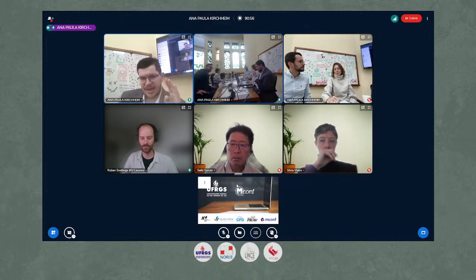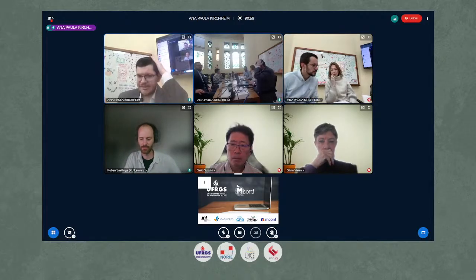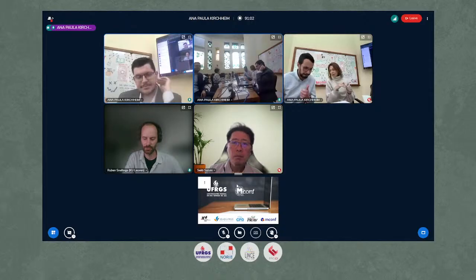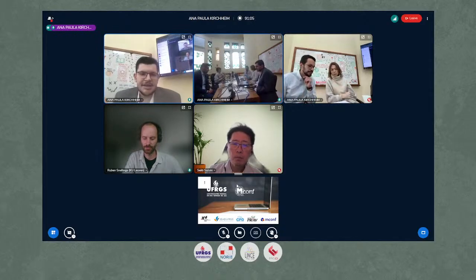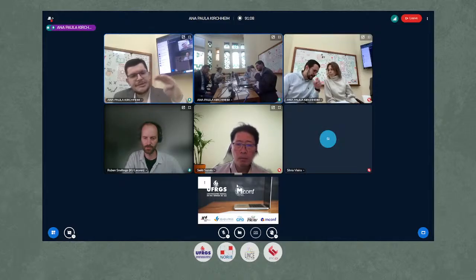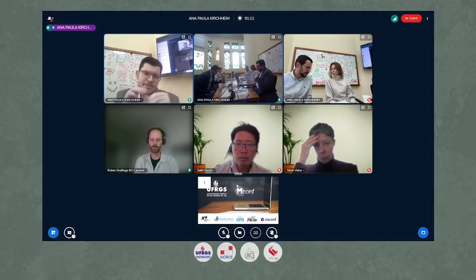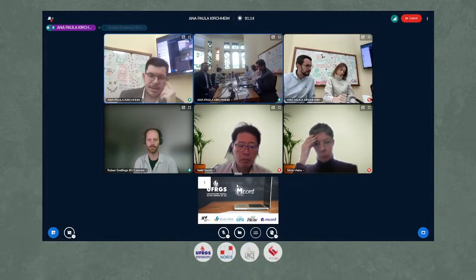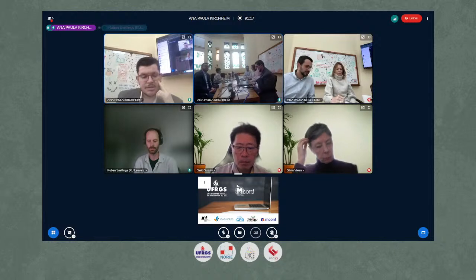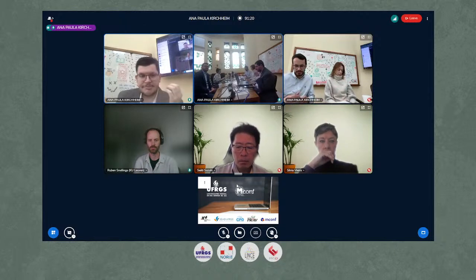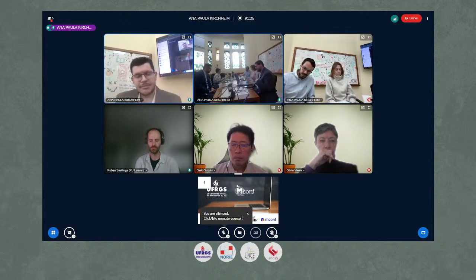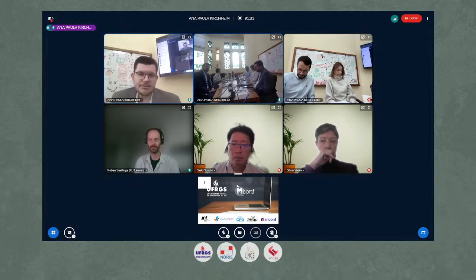C4AF was okay, I think, with the iron compared to the other phases, but especially the C3A, because of the incorporation of alumina in belite. So I saw the biggest difference was the C3A content, because much of the alumina is incorporated in silicate and especially in belite. So I think it would be interesting perhaps to add this as an appendix comparing XRD with both, because I already did this, but I decided not to include it because the papers were already very big in terms of words and results. So I prefer to omit it.